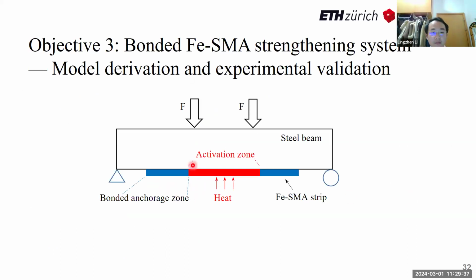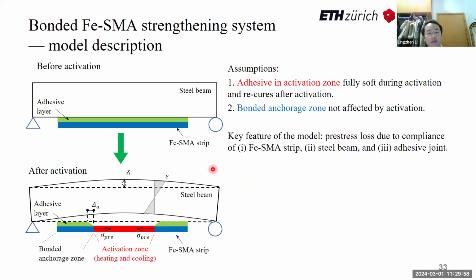Now, we have gained some knowledge in the bonded anchorage zone, and also some about behavior in the activation zone. It's time for us to jump out and analyze the structure member strengthened by this bonded shape memory alloy strengthening technique. After we bond the unprestressed shape memory alloy strip, we add some additional stiffness to the structure member. This is called passive strengthening, whose effect is limited. But after generating prestress, the strengthening is more efficient.